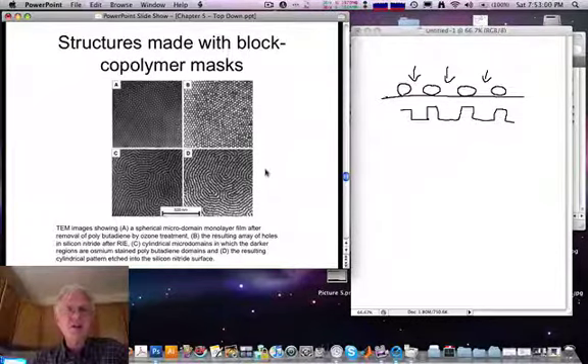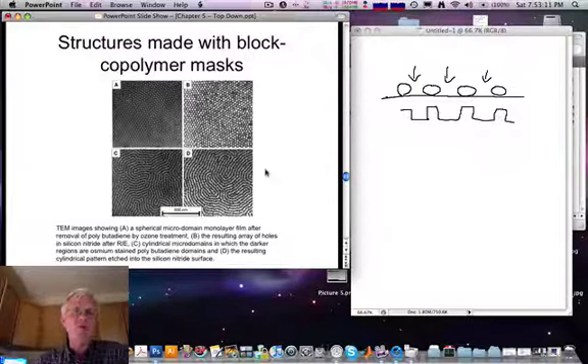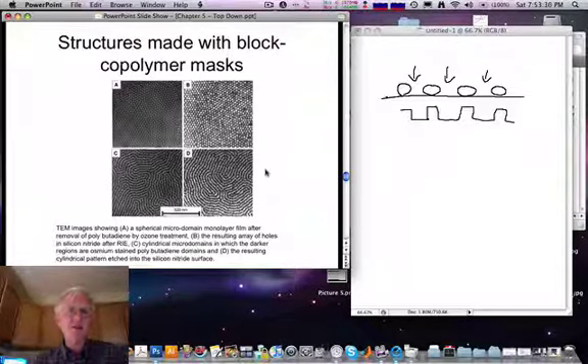Clearly, the disadvantage of this type of masking is that very complex organized structures like computer processors are hard to make. On the other hand, for making, for example, small magnetic structures for hard drives, this is a really wonderful technique, and one that beats the resolution of any type of lithography by a large amount, since masks can be made with features down to a very few nanometers using these techniques.